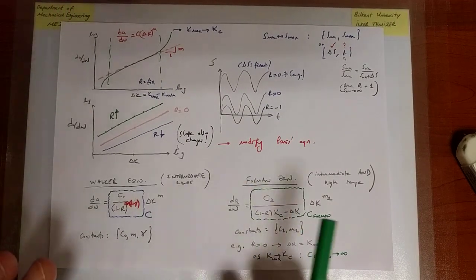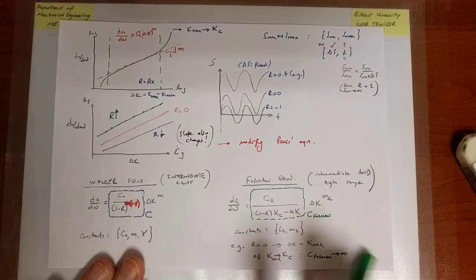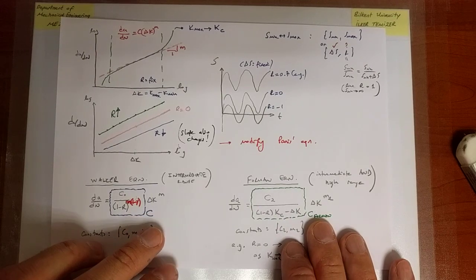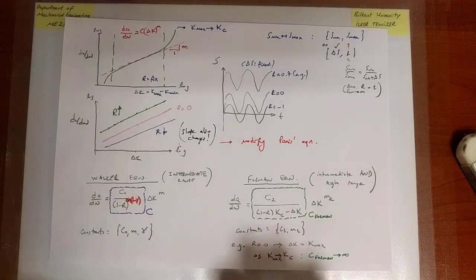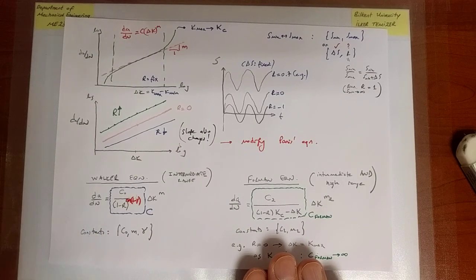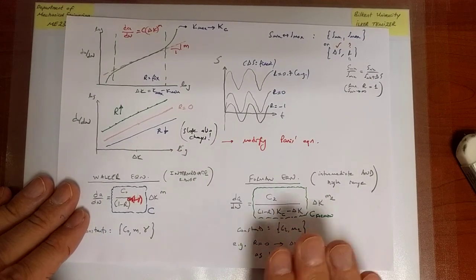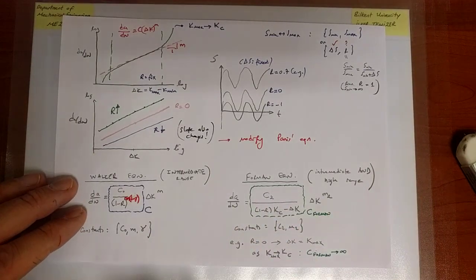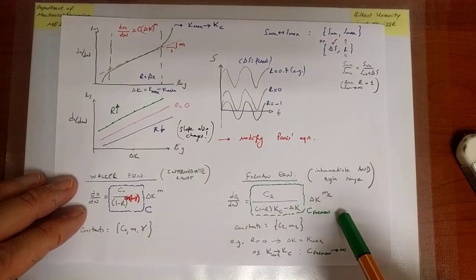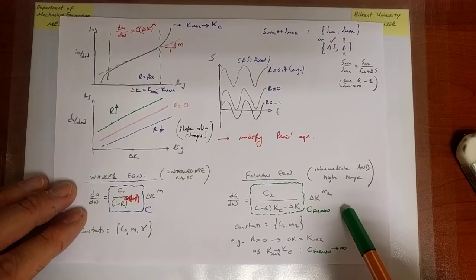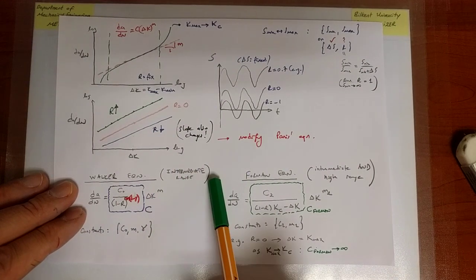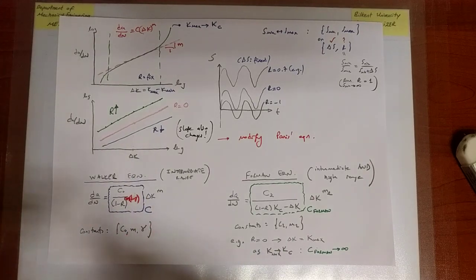Now, having said all of this, we're going to use, in principle, these two equations. Both of them, form-wise, look similar to Paris. That's why we need to know it by heart. But eventually, when you look up in material tables, it's either this or that you're going to look for. If you're considering a scenario where the crack growth is all the way to failure, this is ideally what you would like to use, because this equation takes you all the way to failure. This one not. It takes you up to the high range, and after that it is under conservative.